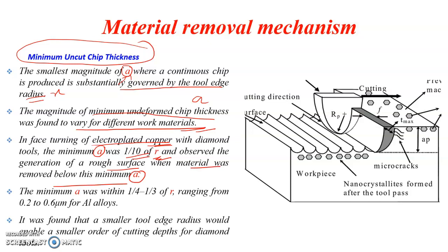So we can't go below this minimum value for A, that is, in this case, 1/10th of R for machining electroplated copper. In an experiment it has been revealed that if we are machining below this minimum A, then the surface roughness increases, otherwise the finish is improved. In another example, this minimum A for aluminium alloys has been found as 1/4 or 1/3 of this R.